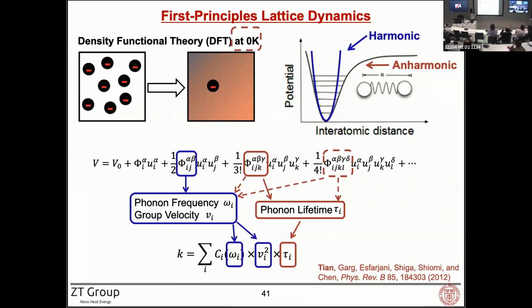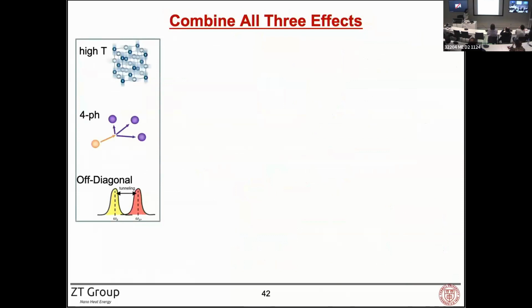And since the DFT calculation we did was at 0K, it's not suitable for those higher temperature phases. And also, we traditionally only consider the different phonon branches as independent. They don't really tunnel to each other. So with those three constraints, we want to make some advancements by looking at the high temperature phase, including full phonon scattering, and considering this off-diagonal term interactions.